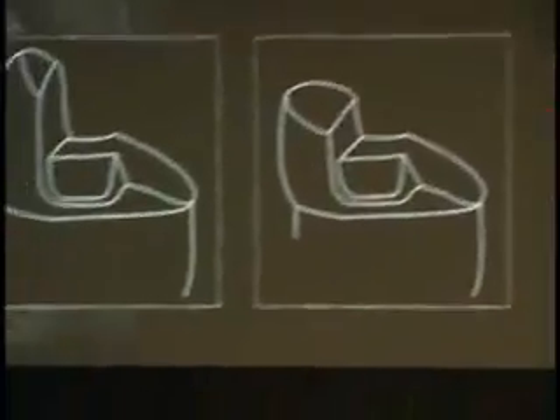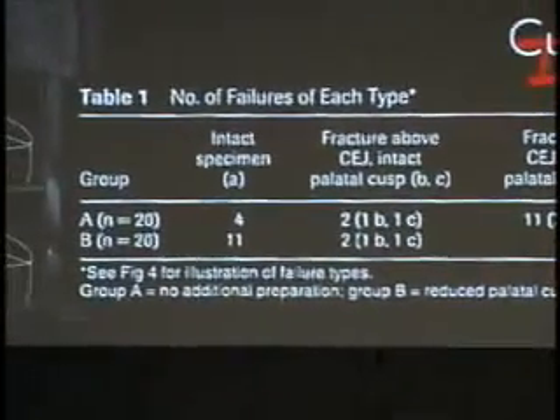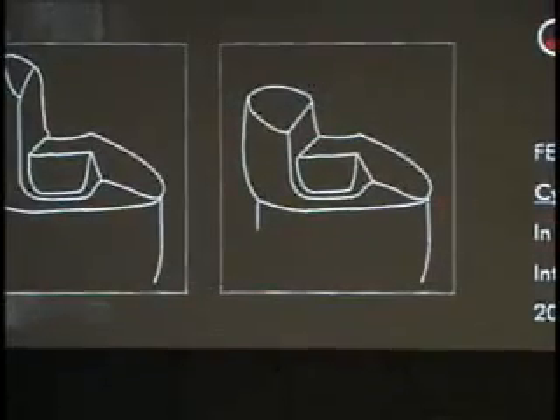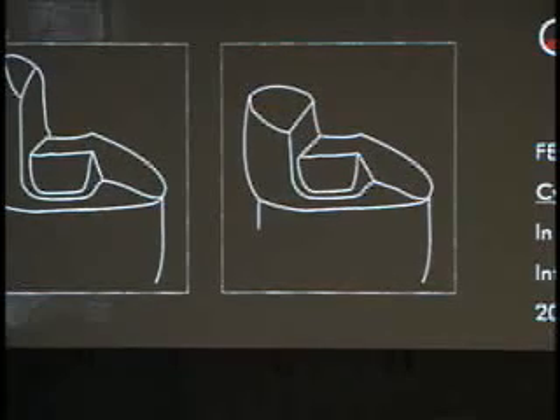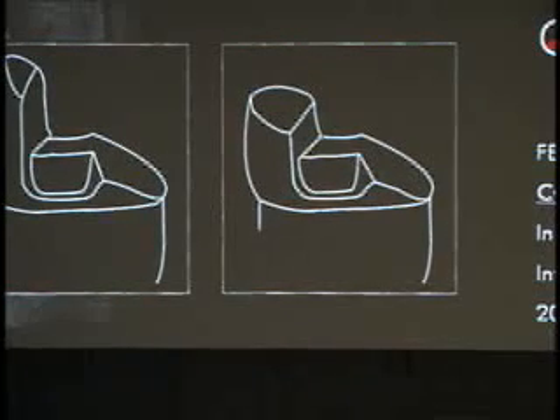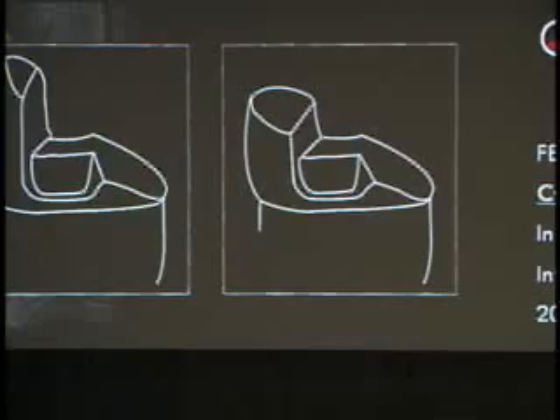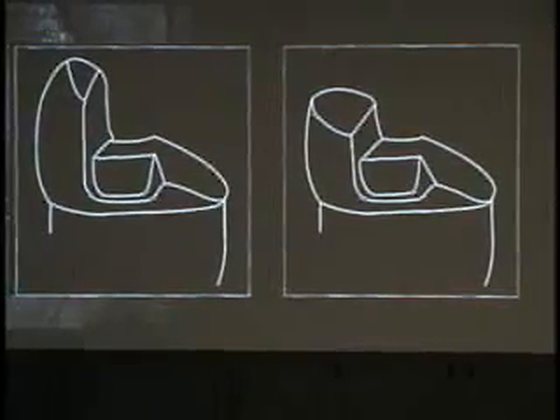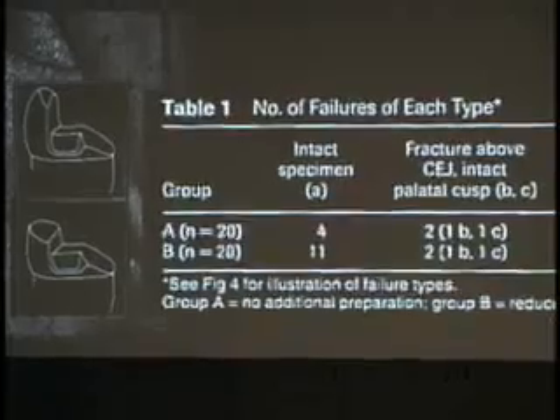What is the effect of cusp coverage? I told you, if you cover a cusp, even if you do that with composite, like in this study, you are significantly increasing the strength. In that case, design B, in which the buccal cusp was covered, gave much more survival in that test. And that test was basically, again, a number of cycles until failure using a ramp loading, a progressively higher load during the cycling test. So again, if you cover, you strengthen.